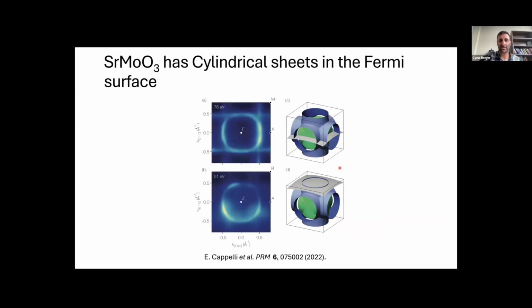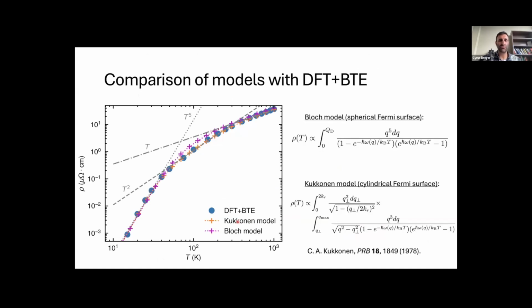And so strontium molybdate and strontium vanadate have cylindrical Fermi sheets in their Fermi surface, which has been shown with calculation and also with ARPES. And when we use the model of a cylindrical Fermi surface, that is these magenta points here, these orange points here, we see that we can capture this T-squared regime that we see in the full DFT plus Boltzmann transport equation calculation. Whereas what I label as the Bloch model, which assumes a spherical Fermi surface, can capture the T to the fifth and the T linear, but this regime here is just a crossover between the two. It doesn't have a true T-squared regime. So in this way, with a cylindrical Fermi surface, we really can get a T-squared regime from electron-phonon scattering.